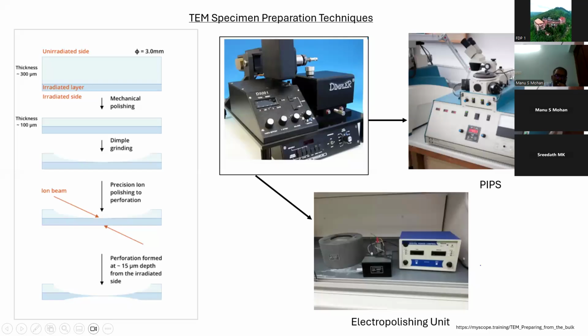A dimpler means a wheel will be revolving, rotating above the specimen, making a hole. You have to be careful, because if the depth is reduced too much, you will not get the electron transparent region. The purpose is to produce an electron transparent region through which the electron beam will pass. In transmission electron microscopy, as the name says, the electron beam will be transmitted through the specimen - that is one of the important criteria. So your specimen has to be made electron transparent.